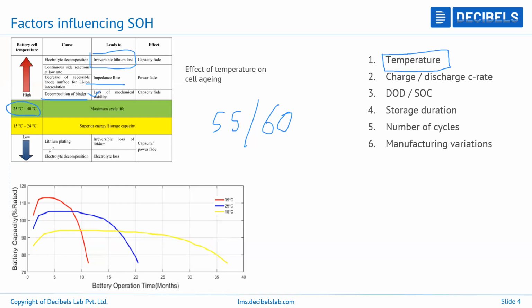Similarly, if you go to very low temperatures like 10 degrees or 0 degrees, or sub-zero temperatures like -10, then you will have something called lithium plating and another very dangerous phenomenon called the solid electrolyte interface. If you keep operating at very low temperatures, this interface will block the reactions from occurring. It is a hindrance to the mechanisms and will act as a very high resistance. It is basically a layer that builds up on the electrodes and prevents the effective reactions from occurring.